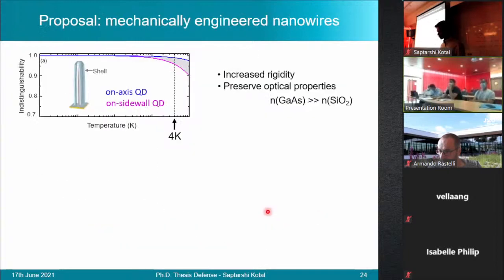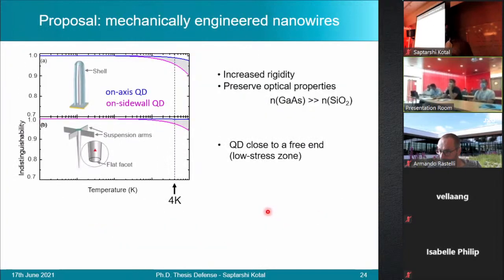The second solution could be to suspend the nanowire from the top, thereby leaving the quantum dots at a free and unclamped end, thus reducing the stress that they experience from the modes. In this case, we now see that in the worst case scenario the indistinguishability goes up to 97%.